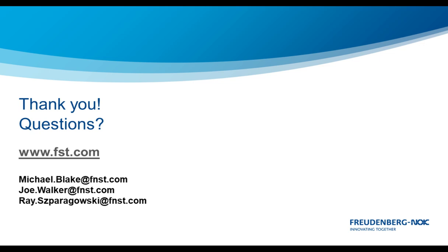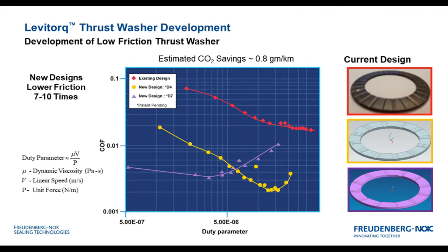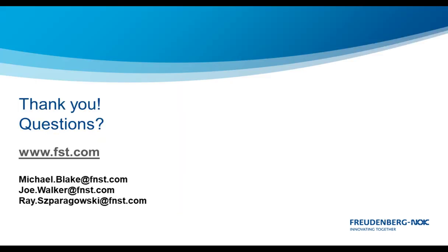Oh, that's another good question. When you change fluid viscosity, like many of the new fluids that we're going to use to improve efficiency, you actually change the amount of fluid film you can generate. So when we create one of these Stribeck curves, for example in the Levitorg slide I'm calling up now, you can see that friction is lowering as we change speed. But in effect, by changing the viscosity of the fluid, you're shifting the curve. Lower viscosity fluids would run much lower film thicknesses and would actually run drier, making the curve move to the left-hand side. So you have to then try to compensate, because if I have a rough surface, I have to have a fluid film thickness large enough to overcome the contacts of those roughnesses. So very significant impacts.